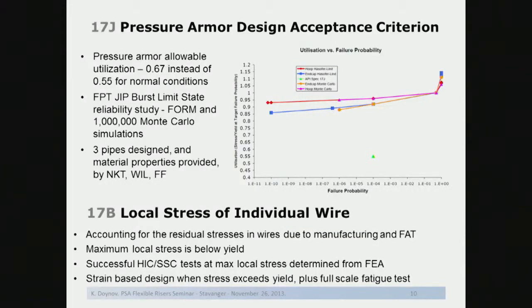is a reliability study that we performed during the flexible pipe technology JIP, which was based on the first order reliability method and Monte Carlo simulation, about 1 million of them, for 3 pipes, with design and material properties provided independently by the 3 flexible pipe manufacturers, NKT, which is nowadays NOV, Wellstream, and Technip Flexi France. So what you see on the graph, on the horizontal axis is failure probability, and on the vertical axis is stress utilization normalized by the yield. And this green dot here represents the current design criterion of 55%, which is positioned at probability of occurrence 10 to the minus 4.